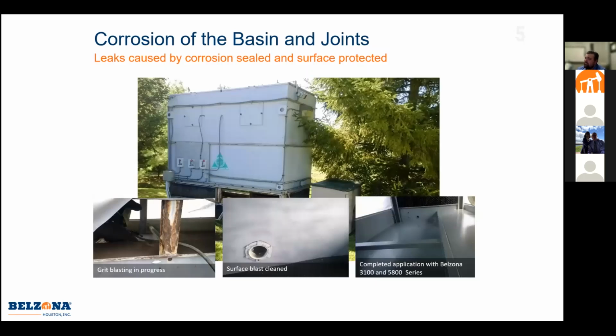Right here is a little smaller unit. A lot of times most people don't coat these because it's hard to get into. It's hard to really get people in. We can do this no matter how small, really. We can get something in there in order to prep the surface properly and coat it. This is another little before and after where we're doing grit blasting. Got it blast clean, and then we coated it with the flexible membrane and then our 5800 series 2-coat epoxy.